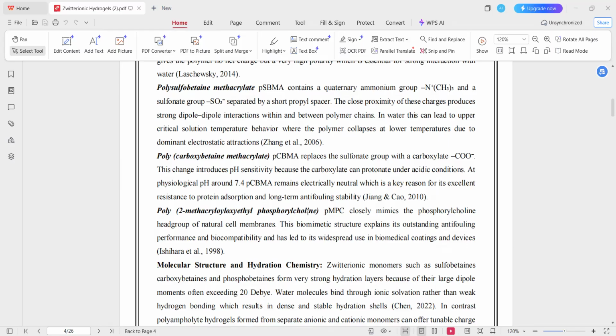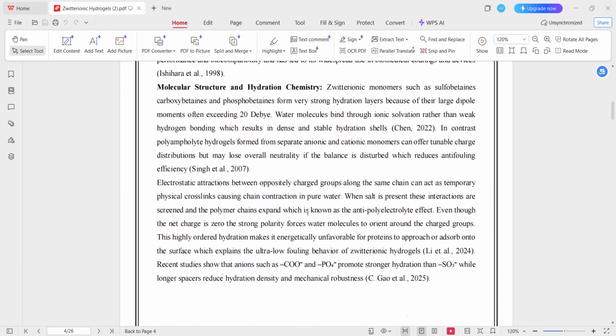If we talk about the molecular structure and hydration chemistry, the hydration behavior of zwitterionic hydrogels is exceptionally strong because zwitterionic monomers possess very large dipole moments, often exceeding 20 debye. This strong dipole attracts water molecules primarily through ionic solvation rather than simple hydrogen bonding. As a result, water molecules arrange themselves into dense and tightly bound hydration shells around the charge groups. These hydration layers are highly stable and remain intact even in salt-rich environments, which explains why zwitterionic hydrogels maintain their properties under physiological and marine conditions.